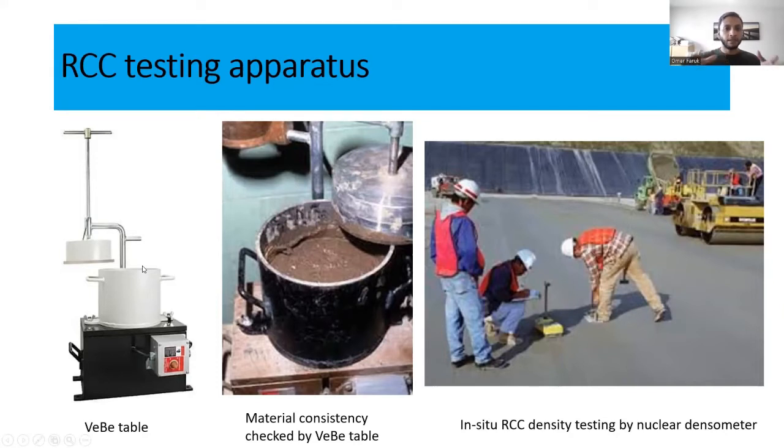You first put your material into the cylinder, and then you install the surcharge over the material, and then you start to shake the table. You will notice that around the surcharge, material or paste starts to come up, and we count how long it takes for some paste to show around the surcharge. The time required to bring the paste up is already predetermined in the laboratory test, and that gives us an indication of whether the material in the truck